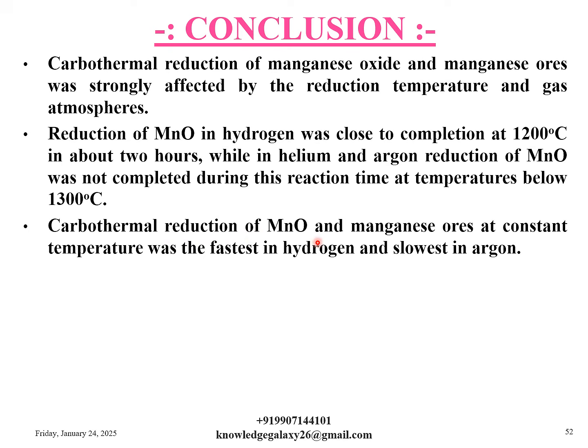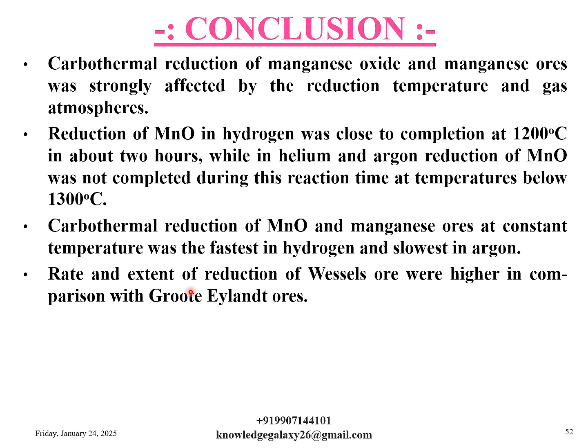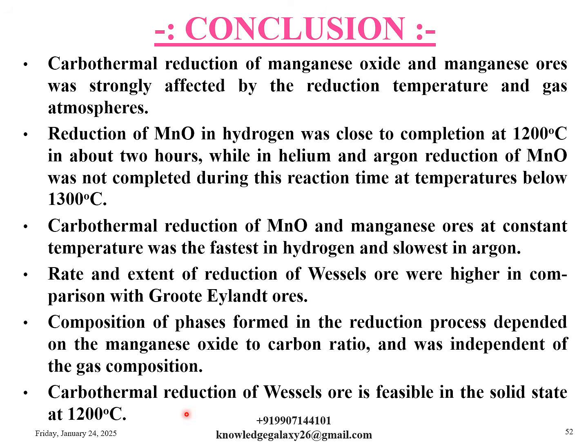Carbothermal reduction of MnO and manganese ores at constant temperature was the fastest in hydrogen and slowest in argon. Rate and extent of reduction of Wessels ore were higher in comparison with Groote Eylandt ores. Composition of phases formed in the reduction process depended on the manganese oxide to carbon ratio and was independent of the gas composition. Carbothermal reduction of Wessels ore is feasible in the solid state at 1200 degrees Celsius.